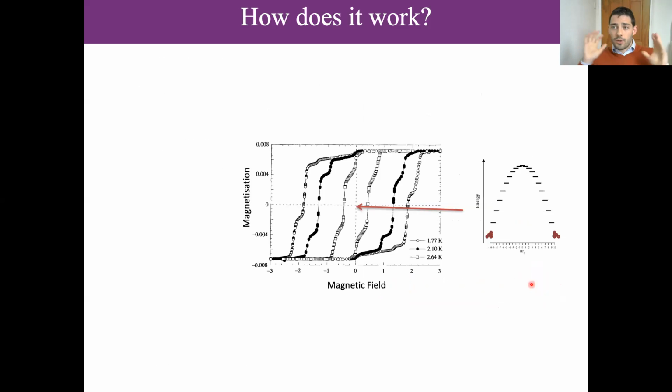So just now that we've got a picture of the electronic structure in mind, we're going to revisit this hysteresis diagram. So in full equilibrium, in zero magnetic field, at some low temperature, we would have 50% of the population of our ensemble of molecules on one side of this diagram and 50% on the other. They are degenerate in energy, so we have equal populations. If we magnetize the sample, then the energy levels are biased, and so we will have some reshuffling of the molecules towards their lowest energy state.